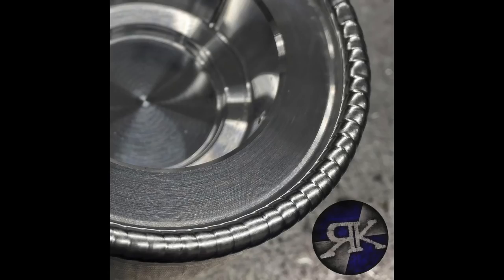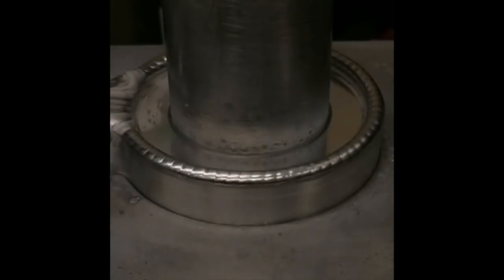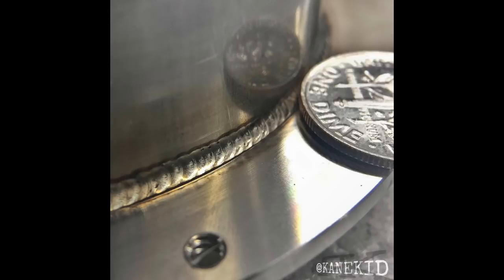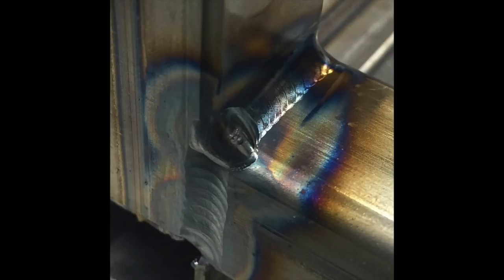It's funny, it's actually termed in a lot of cases as a brazing rod for aluminum because it melts at about 100 or 200 degrees less than the base metal, a little bit lower melting point than 4043, just enough that they call it a brazing rod. Hypothetically, you weld a fillet on 16 gauge aluminum with 4047 and you cut and polish and do a macro specimen on that, it looks almost like a solder joint. You can flow it in there where there's absolutely no depth of fusion, but it's bonded, just like a braze joint would be. So it is a little weaker on its tensile properties than 4043, but a lot of times it's good enough. And if I was patching a crack on a crankcase on a Harley that was polished aluminum, I would grab that because it'd be a lot less likely to have porosity when it polished out.